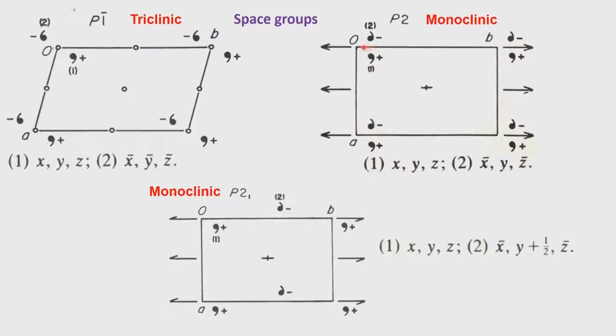And then we also have the possibility of the same special position coming at the repeat distance along the A direction. So, other than that, we have only the general positions x, y, z and x bar, y, z bar, and this generates 2 equivalent points, and the equivalent points on one translation take the objects outside of the unit cell, and so therefore, z is always 2 in P2.